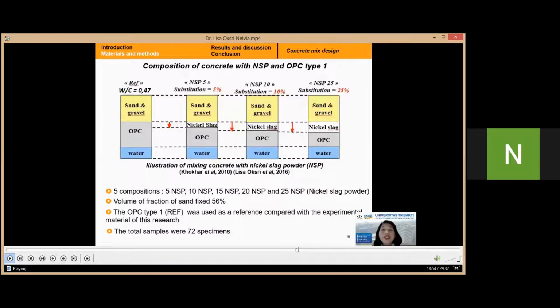To use the nickel slag as a supplementary cementitious material, or what we call SCMs, the concrete was designed on the Japanese Industrial Standard JIS A 5004, with almost 56% sand in the total aggregate volume, the fraction of sand fixed, and the water-cement ratio of 0.47. For testing fine aggregate and coarse aggregate based on the standard, the fine aggregate passed the cleanliness test. Ordinary Portland cement type 1 used was Tiga Roda. The composition of the concrete mixture was compared with the compressive strength target of 30 MPa.